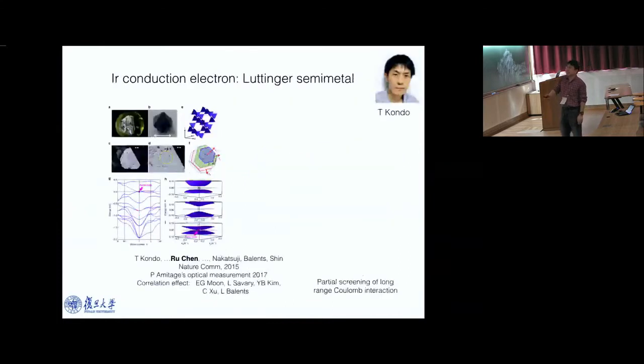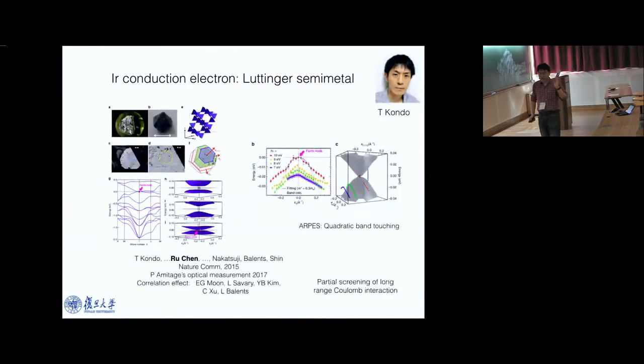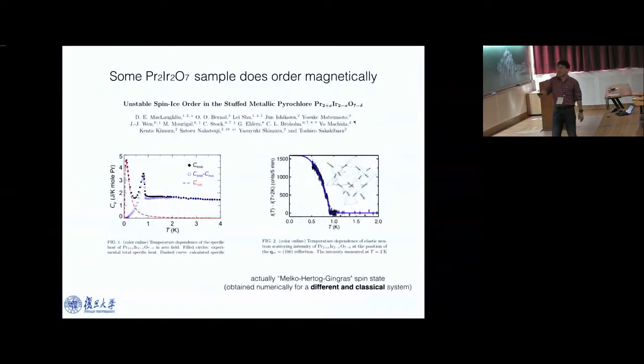So that's the ARPES result, the angle-resolved photoemission measurement, which measures the conducting electron band structure, right? Apparently some other samples have been made very recently, and they develop magnetic order if you change the stoichiometry a little bit. Because some samples develop magnetic order if you change the stoichiometry, it can be measured by neutron diffraction measurement.